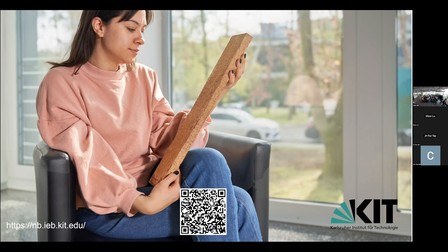We have done a lot of studies on that. First of all, using natural bamboo in concrete has major issues because of durability. It doesn't last long. After a while, if there is humidity or water penetration in the concrete, the bamboo becomes like your normal timber product that you buy: if water gets in, it starts to expand. Bamboo is the same, especially in natural form. Once it expands, the concrete cracks, and that's why use of natural bamboo in concrete is not advisable, especially for housing. But for shelters, where you house people for maybe 6, 8, or 10 months, that's fine.